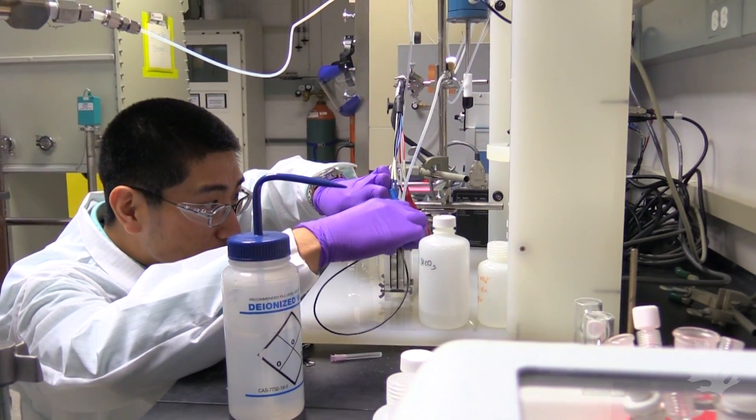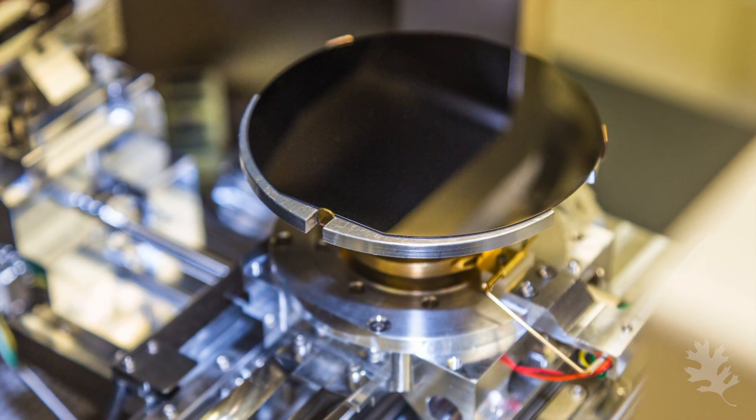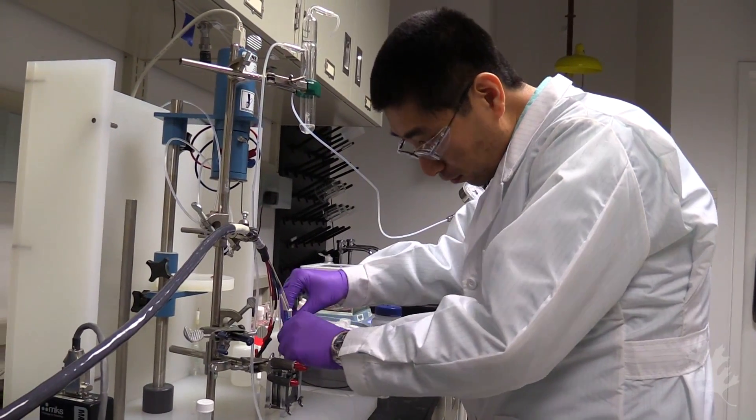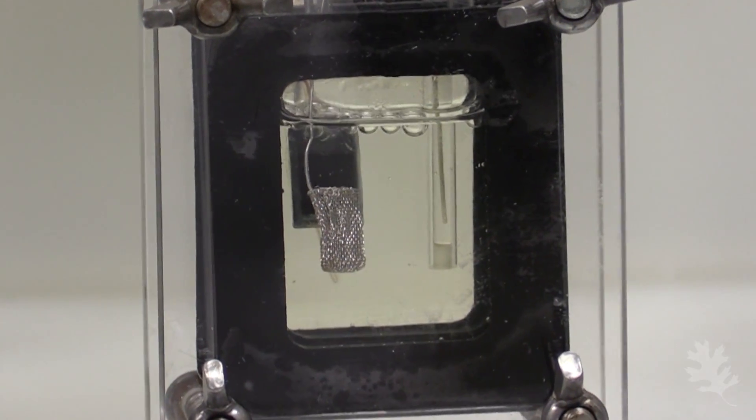One of the nice things about this catalyst is it actually has a yield of around 63-65%. We've measured as high as 70% depending on the sample, which means that of all the carbon dioxide and all of the electricity that's going into it, you don't waste much of it. The majority of it ends up actually converted to ethanol.